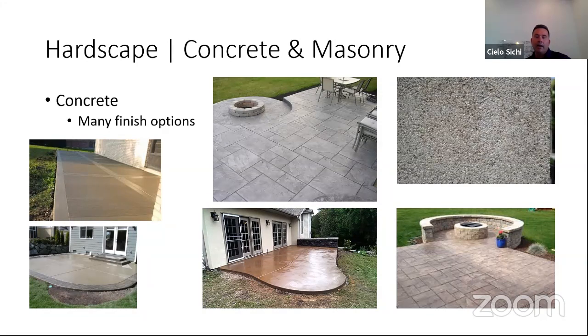I prefer just a simple colored concrete with a sand finish, no stamp. And I prefer to not seal concrete. Sealing any kind of stone or concrete surface can tend to be very problematic because what you're doing is sealing the very top layer of it, right? The bottom layer of it is in contact with ground, which in the wintertime gets wet and it absorbs moisture. And as it absorbs moisture, there's salts in it. And that can push the salts up and out of the concrete.